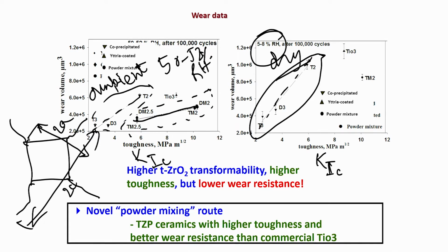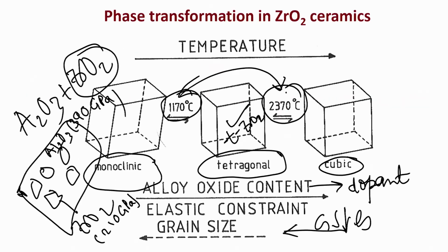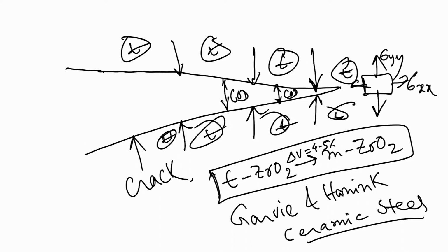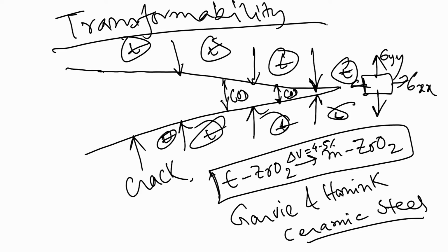So, what it means is that it is important to tailor the fracture toughness properties, because higher fracture toughness essentially means higher tetragonal zirconia transformability. Transformability, if you go back to my earlier sketches, essentially means the ability of tetragonal zirconia to transform to monoclinic zirconia in the crack tip stress field. So, the higher the transformability, the higher the potential of tetragonal zirconia to transform to monoclinic zirconia. This is very important for you to remember.